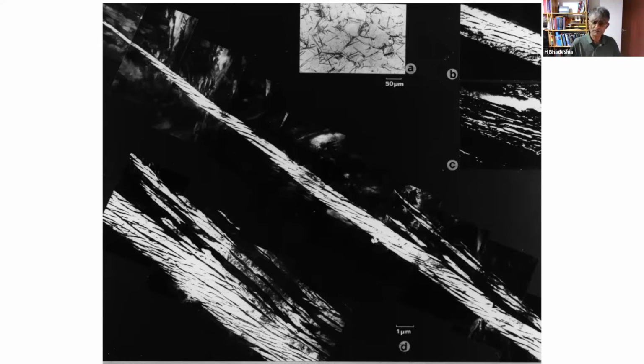So this is very important, because if you look at the transformation at a low resolution, and it's important to look at low resolutions, then you will be picking up the growth rate of this object, which includes the time taken for subsequent plates to nucleate, rather than the growth rate of the individual platelet. And we also need to know why they stopped to a limited size before they've met any hard obstacles.